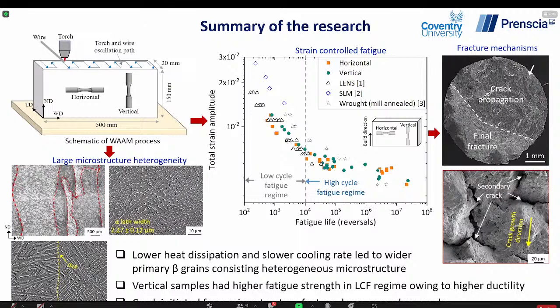So on the right-hand side in the middle, you can see the overall strain control fatigue results of the WAAM Ti64 sample, which is in the filled symbols, compared with the literature data, which is in the open symbols. Just for clarity, I have highlighted the low cycle fatigue regime and the high cycle fatigue regime within this plot.